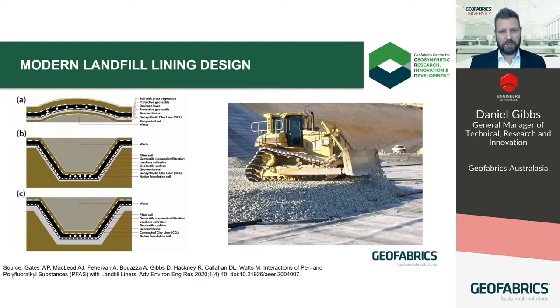The improvement in hydraulic performance of a composite lining system over and above the individual components is well documented. But what about the transport of PFAS? There's been some recent work carried out by researchers here and overseas, which has shown that while PFAS can form micelles, as we saw in Will's talk, at higher concentrations and reasonably readily diffuse through the amorphous regions of polyethylene geomembranes, diffusion may be very low for the concentrations we find in a typical landfill setting.